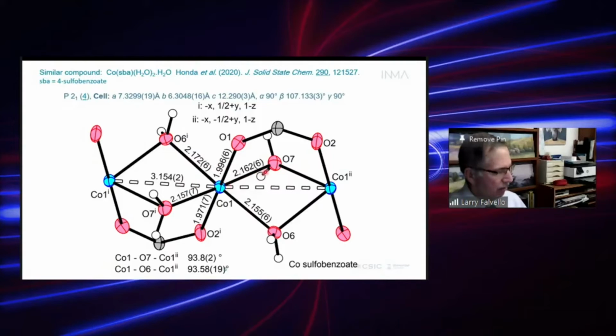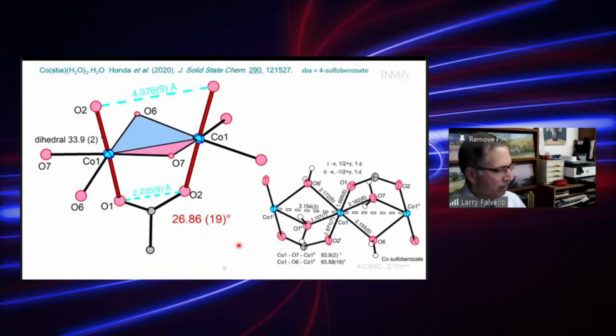lengths to point out, which is that the angle at the bridging oxygen atom, cobalt, oxygen, cobalt, is in the range of 93 to 94 degrees. But what these authors pointed out was it was below 97 degrees. And 97 degrees is what they cite as the limiting angle for promoting ferromagnetic superexchange. Otherwise, the geometrical parameters of this are very similar to ours.